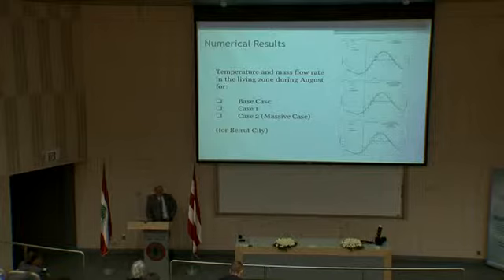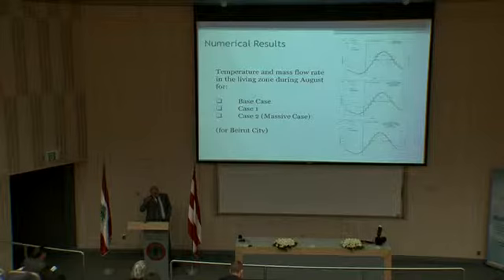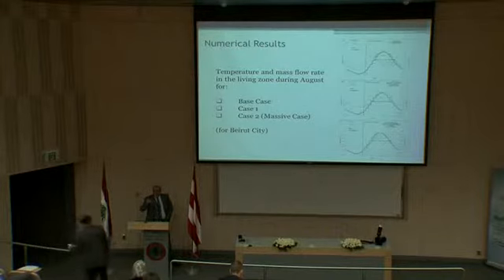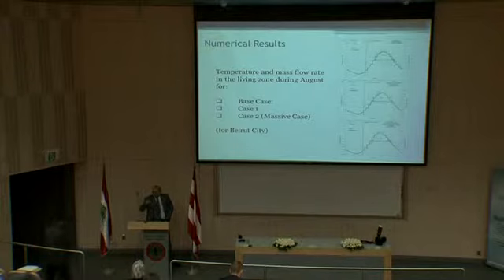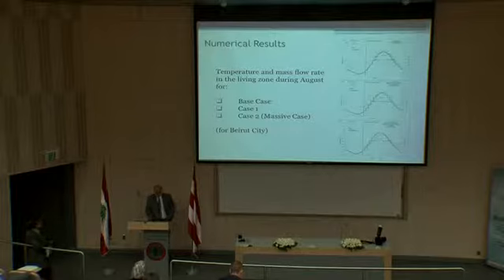We also studied the summertime, where the indoor temperature can get higher. We noticed that in the living zone, the controller was trying to prevent the temperature from getting higher than the outdoor temperature. The controller was unable to bring the temperature to 26 degrees, but it did prevent it from getting higher than 26 degrees, and we can see the periods where we had to use the fan.